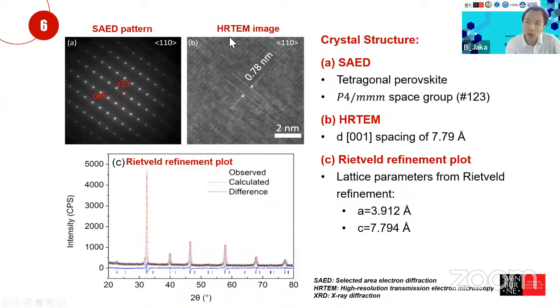here, and then also on the HRTEM image, we can get the lattice spacings for this particular material. 0.78 in here for the plane of 001, and then we are able to conclude that this particular structure has a tetragonal lattice with the space group of P4/mmm, okay, where we have an a of 3.912 with the c of 7.794. So this is not a cubic structure. It's basically because we have something that is a bit longer in one direction with respect to the other directions. So here we have the tetragonal perovskite lattice.